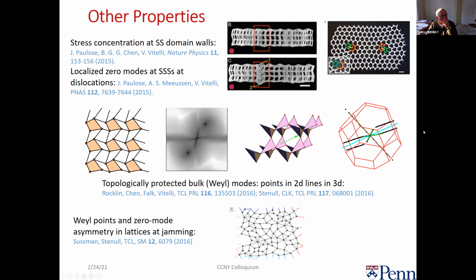There's something called the dice lattice. The dice lattice is one where you have sort of two interpenetrating square lattices, I guess. How does it go? I've forgotten the details of how that looks. There are models where you get an average coordination of 4 by alternating 3s and 5s. I see. You can use the analysis I just gave for that system. Of course, you have more sites per unit cell. So things get a little bit messier, but indeed you will have basically the same story.